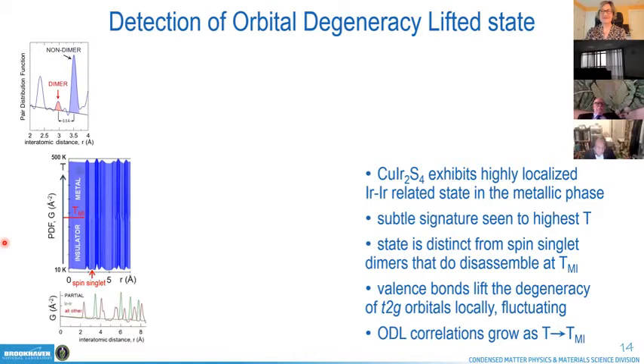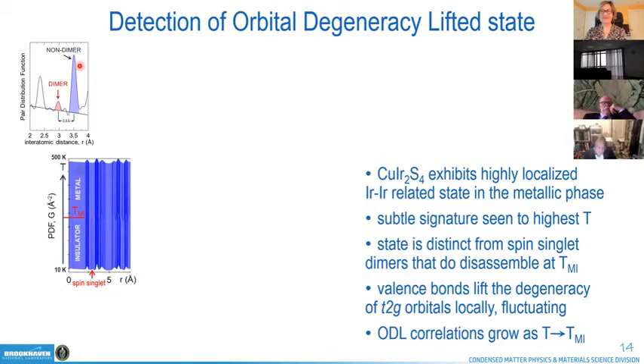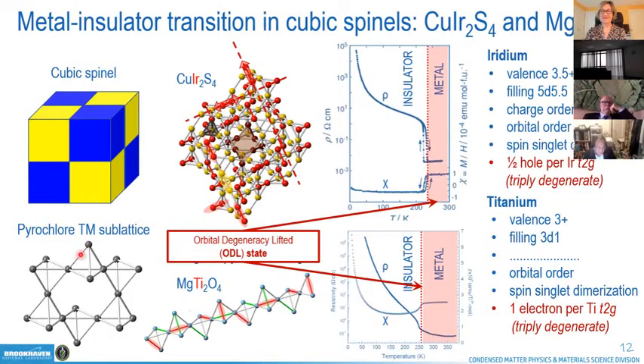For what follows, I'm going to show you here at the bottom a calculation of the decomposition of total X-ray PDF of this system into iridium-iridium pairs, shown here in green, and its complement shown in red. And so what you see is that this very tall peak is the nearest neighbor iridium-iridium peak, and there is very little or almost none of any other contributions. So by looking at this peak, we're essentially looking at the direct structural signature of t2g orbital overlaps in this system, because nearest neighbors are on the pyrochlore sublattice of, in this case, iridium, and t2gs run along those edges.